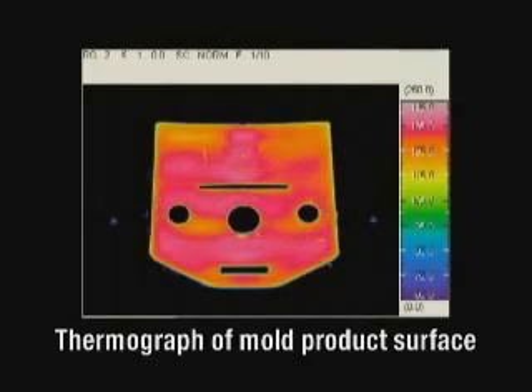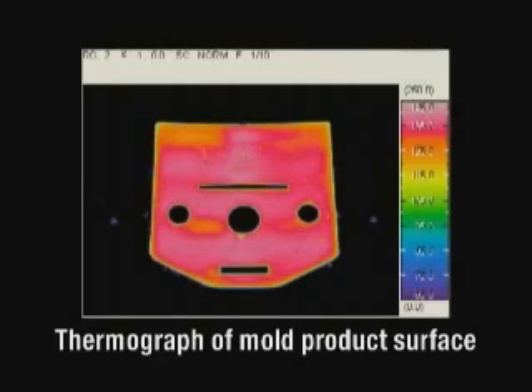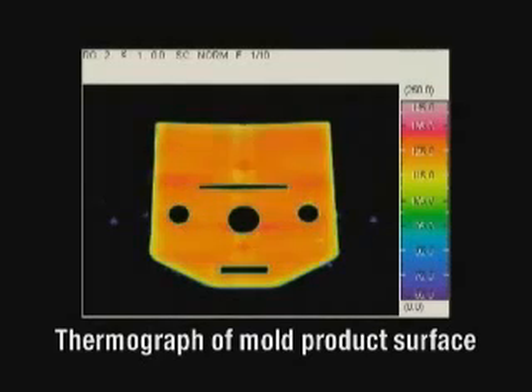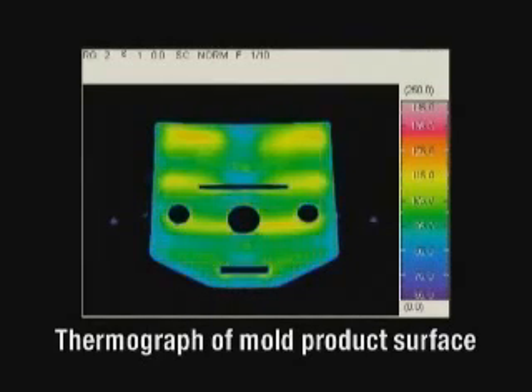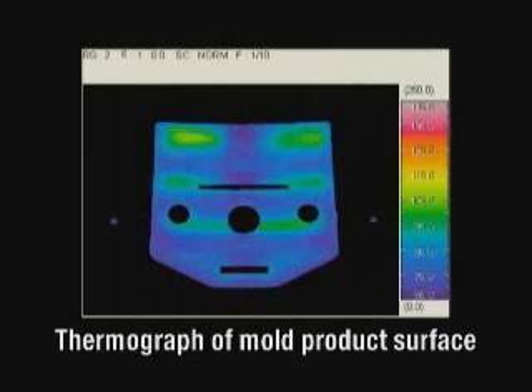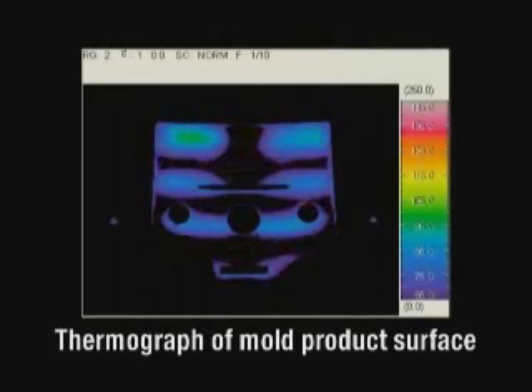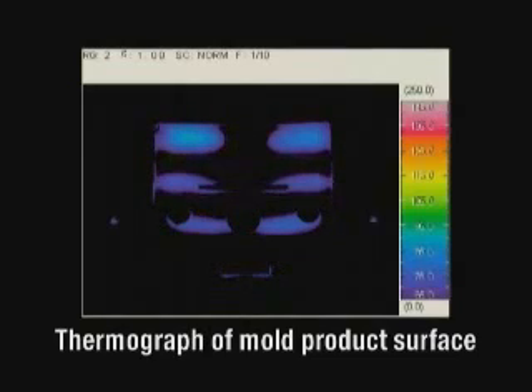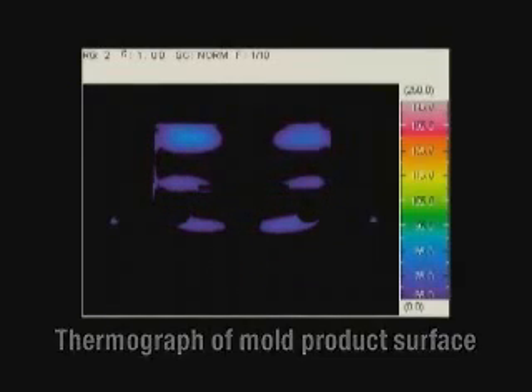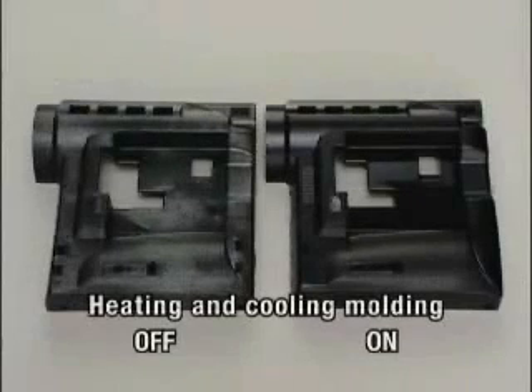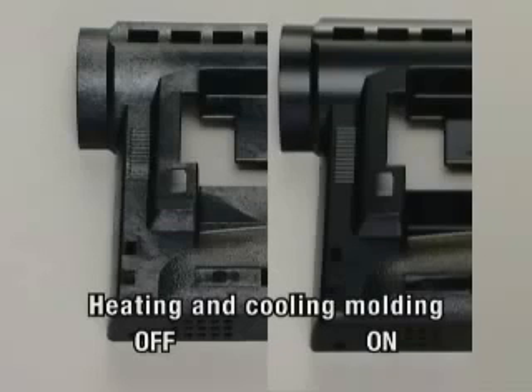The mold temperature can be raised within the time of opening for removing the product. Moreover, the cooling time can be shortened because there are more channels as compared to the conventional mold. The result, high cycle molding without weld lines, sink marks, or warping. This comparison is for the cases with and without performing heating and cooling molding. The comparison reveals that heating and cooling molding makes the resin surface quality considerably different.